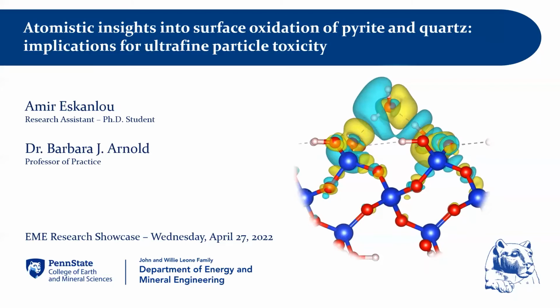Our perception on quartz and pyrite: on the quartz surface, we know that when the surface gets altered, we have the formation of free silanols, and then these surface siloxanes interact, get hydroxylated, and we have isolated silanol or nearly free silanols, or geminal silanol and vicinal silanols. And on the surface of pyrite, when it interacts with, for example, an oxygen molecule, the ferrous iron oxidizes into ferric iron, and as a result of this interaction on the pyrite surface, we have the production of hydrogen peroxide. This hydrogen peroxide then re-interacts aggressively with the mineral surface and brings about the formation of hydroxyl radicals.